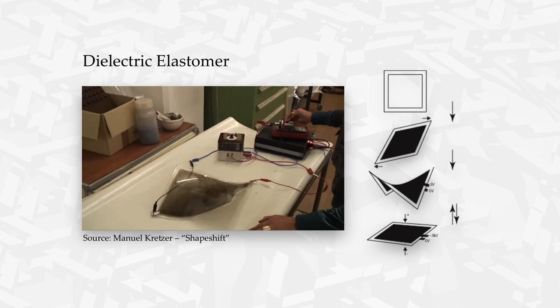This is a dielectric elastomer — a stretchy, rubbery polymer. When you place a different charge on each side of it, it causes the material to compress, and you can design a frame around it that constrains its movement in such a way that the compression turns into all manner of programmable behaviors. This stuff is really cool: it's very cheap, extremely lightweight, silent, fast, and exhibits pretty high strains. It would be perfect, apart from the fact that it requires tens of thousands of volts to operate because it relies on electrostatic attraction — enough to give you a pretty nasty electric shock. Probably not what you want for wearable technology.